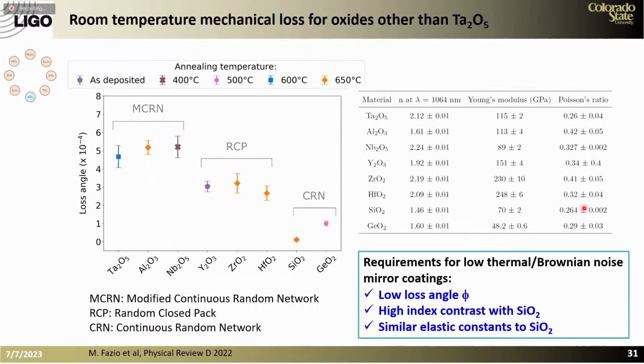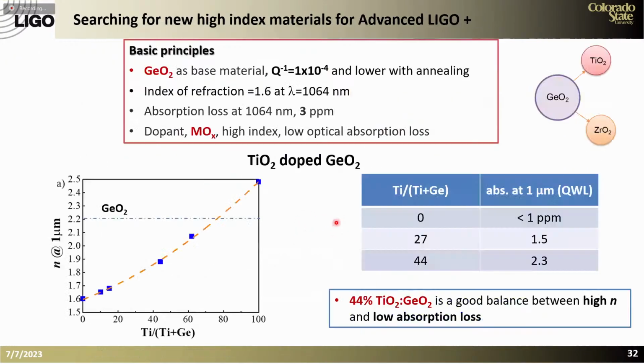So based on this, and because germania has such a low loss angle, what we decided to do is start depositing mixtures of germania with titania, because in this way we can actually affect the refractive index. The refractive index of germania is 1.6 at 1 micron, and that of silica is 1.45.